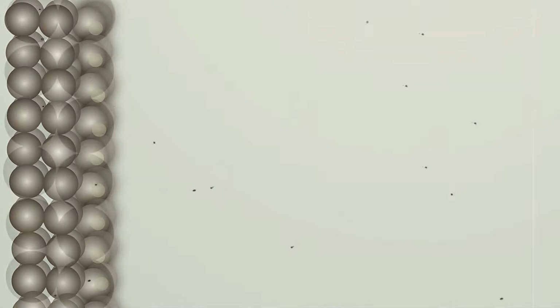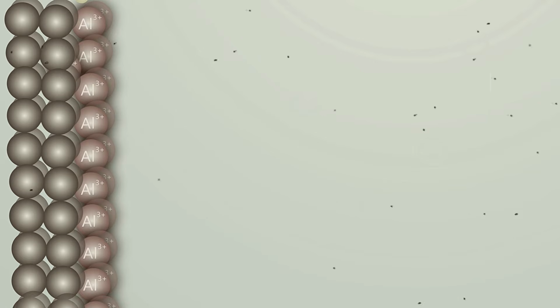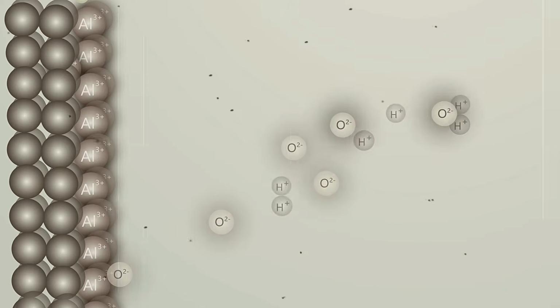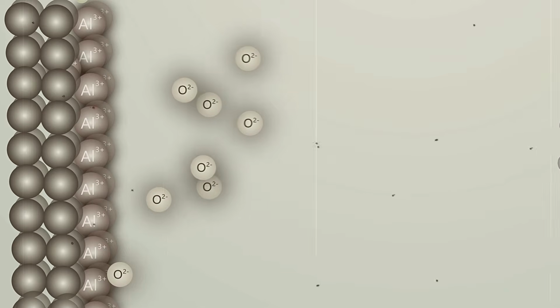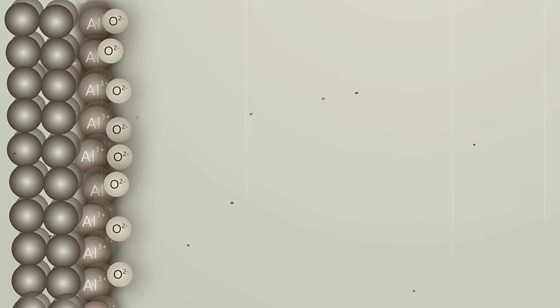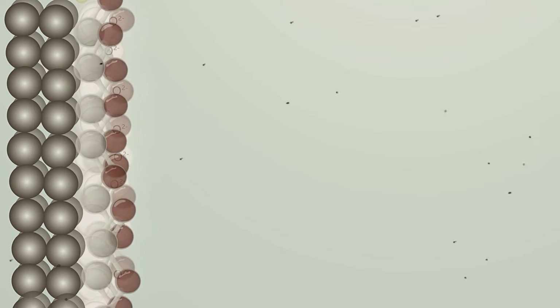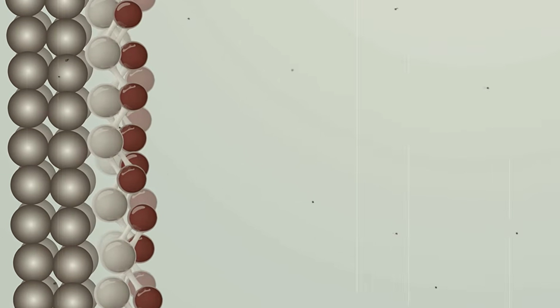Picture a flat piece of aluminum. Now zoom in, past the scratches, past the grains, all the way down to the atoms. Now someone flips a switch, and millions of volts per meter slam across the surface. Oxygen ions slam into the metal, steal electrons, and, in a few trillionths of a second, a perfectly ordered crystal of aluminum oxide begins to grow, atom by atom.